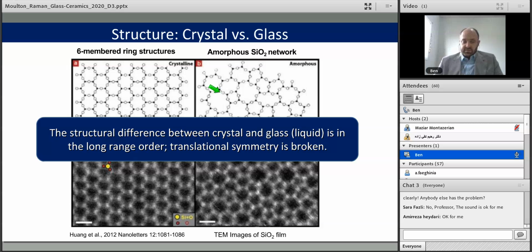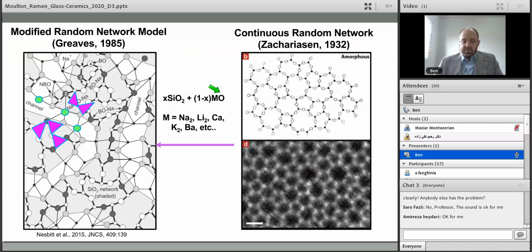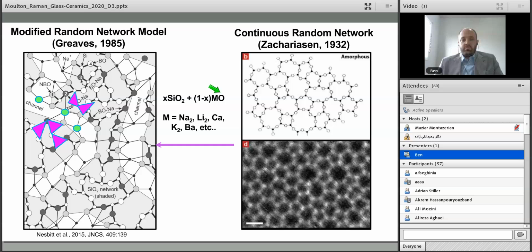While we use silica for lots of applications, such as optic fibers, for most applications we want to have a more complex chemistry. And so starting from Zachariasen's model, Greaves in 1985 came up with a modified random network. As you add a metal oxide here to silicon, with metal elements usually from the left side of the periodic table, sodium, calcium, my favorite, barium, you end up breaking up the network. And so these ring structures that are all nice tetrahedra are retained in this silica region.